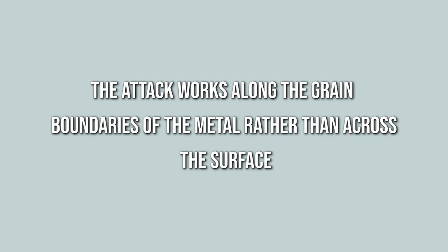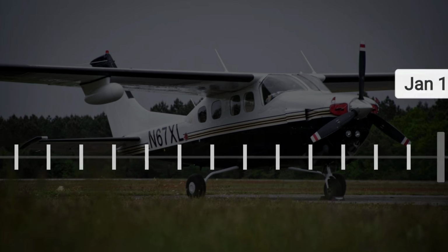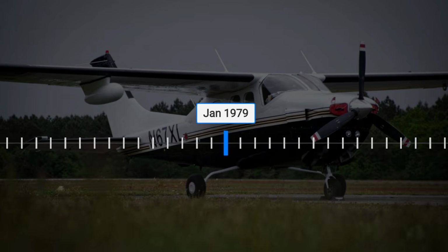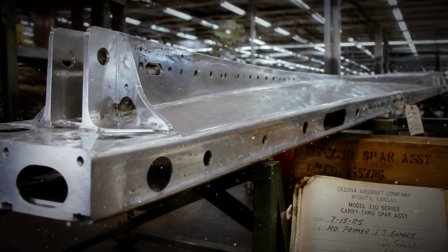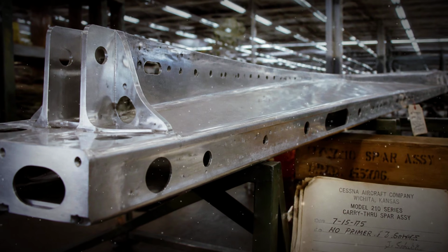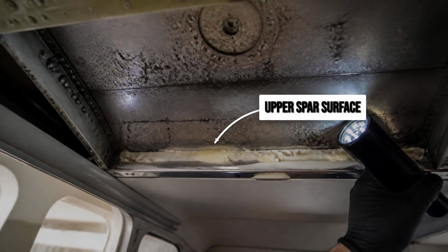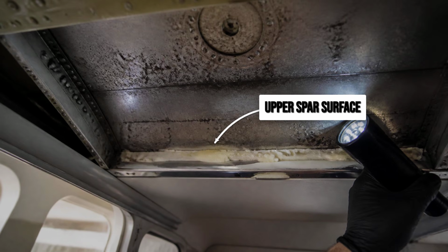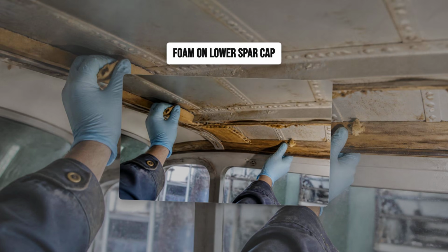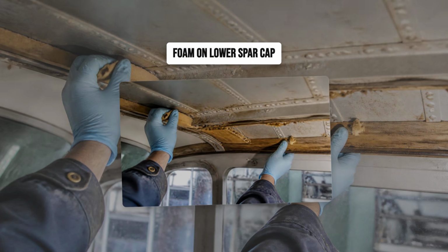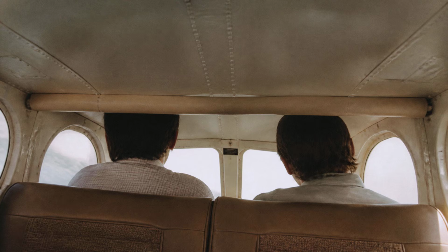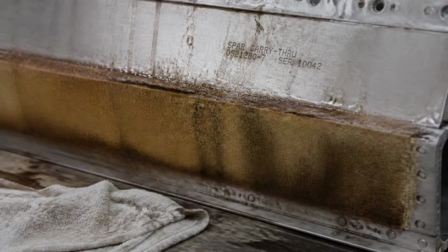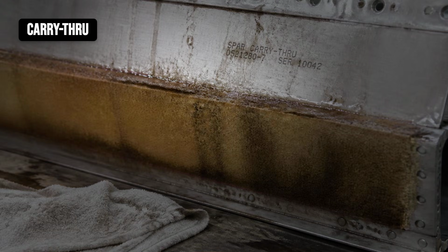The attack works along the grain boundaries of the metal rather than across the surface. Early model 210s, from the 210G through the 210M built through 1979, left the factory without corrosion protection or primer on the spar. Textron's own investigation found the design made the problem worse. The upper surface of the spar sits exposed to the cabin interior, which gives moisture a direct path in. And the factory installed foam padding along the lower spar cap. That foam, intended as head protection for rear seat passengers, traps moisture directly against the unprotected aluminum.